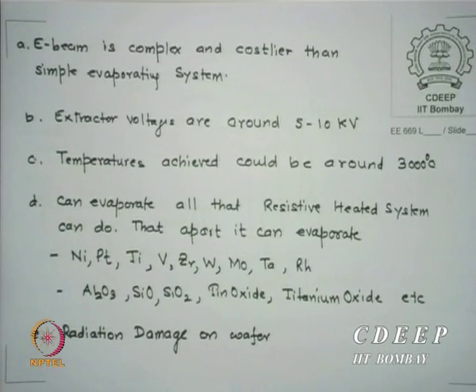The typical extractor voltage is 5 to 10 kV. At 10 kV, temperatures people have reached up to 3000°C, but typically it should be around 2000 to 2400°C under normal conditions. Otherwise, the cooling system requires a huge amount of infrastructure for a 3000-degree hearth. So while it is possible, it is not normally used for 3000°C heating.